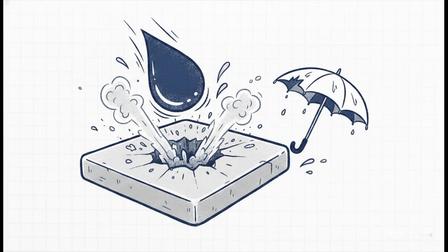And speaking of flaws, let me let you in on a very surprising weakness of this super material. Despite being this rock-hard ceramic, simple water is its absolute worst enemy. Through a chemical process called hydrolysis, if aluminum nitride is exposed to moisture, it reacts to form aluminum hydroxide and ammonia gas. The water literally dissolves the surface of the ceramic over time, totally destroying its thermal and electrical properties. If you're building a water-cooled heat spreader, you have to carefully protect or coat this ceramic, or it's game over.